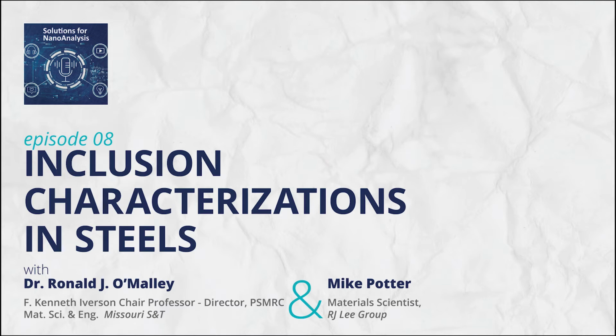I'll take a step back and say, when we manufacture steel today by the electric furnace route, we use a lot of oxygen, and oxygen is used as essentially a chemical energy source in addition to the electrical energy source to actually help melt the steel. But oxygen is also used to remove carbon down to the low levels that are required to make high formability steels, typically below 0.05 carbon, down even to ultra low carbon contents, which might be as low as 30 to 50 ppm. And the oxygen used in that process actually dissolves in the steel. And if you were to take that steel and just try to solidify it as is, you would actually generate gas blowholes, bubbles in the steel during the solidification process.